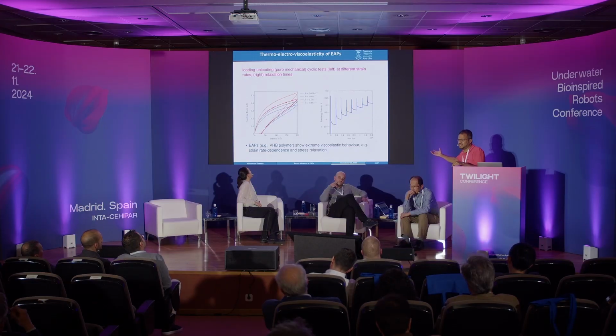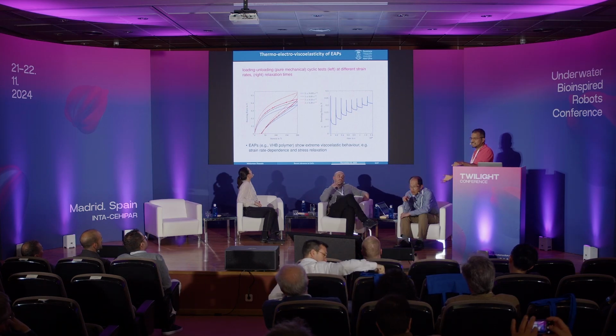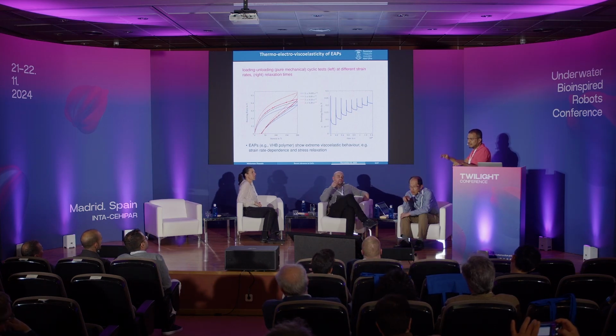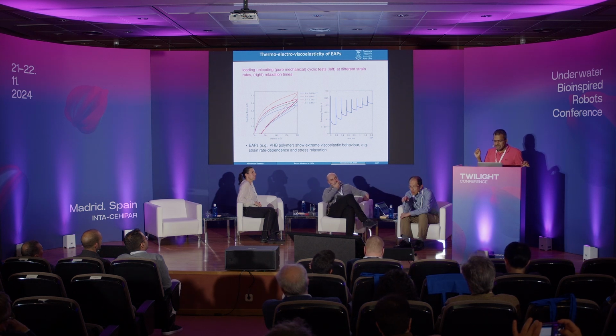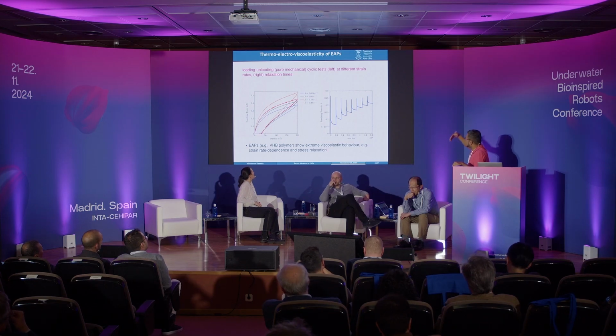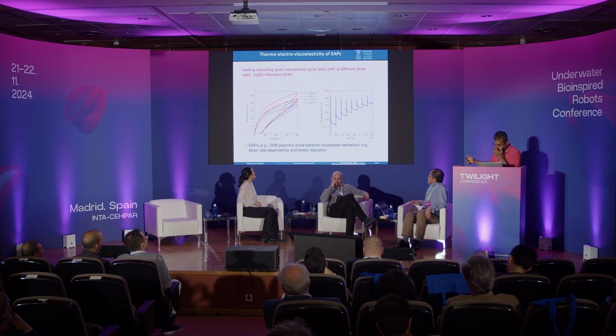So typically this polymeric material is viscoelastic, except 1 or 2% of polymeric materials. Even if someone tells you that I use a hyperelastic model, it's nonsense. None of the polymeric materials are hyperelastic. It's viscoelastic, 99% or 95% at least. That means it is rate dependent, it has relaxation and so on. So you can see the polymer that we have been using, the VHB, is a commercial polymer.